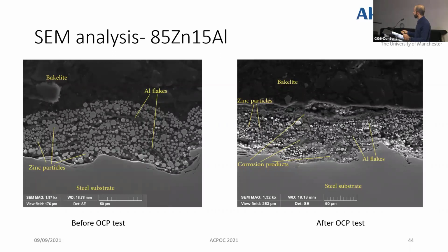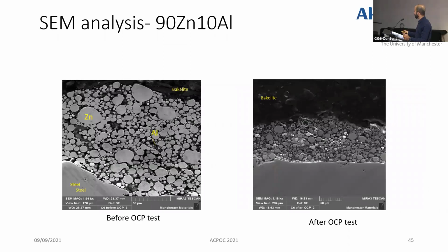For 85 zinc 15 aluminum, you can see the steel substrate is almost intact with full corrosion products in the coating, and there is some continuous path of zinc dissolution that indicates that, although there is still a high amount of zinc unreacted, most of them in some specific paths are reacted and offer some galvanic action, with also accumulation of zinc corrosion product that helps increase the barrier protection. The same situation with the 90 zinc 10 aluminum. Exactly, there is no apparent destruction of the steel substrate over this longer time of immersion.